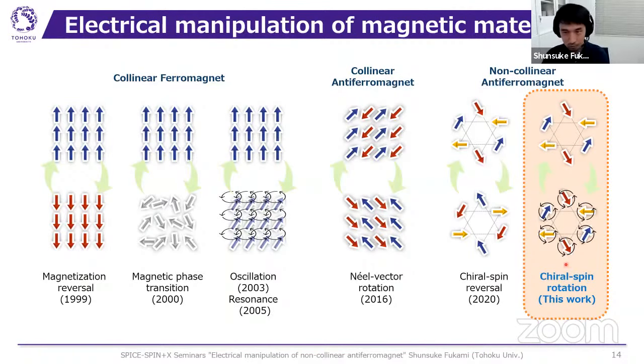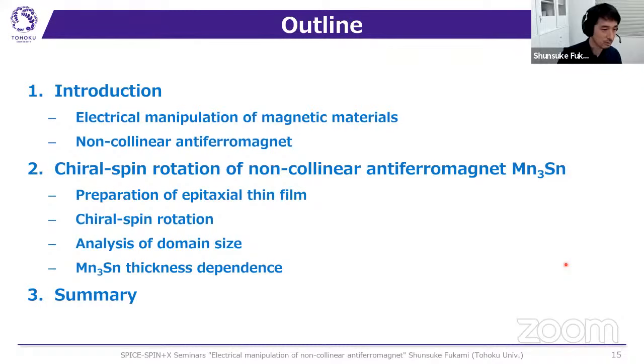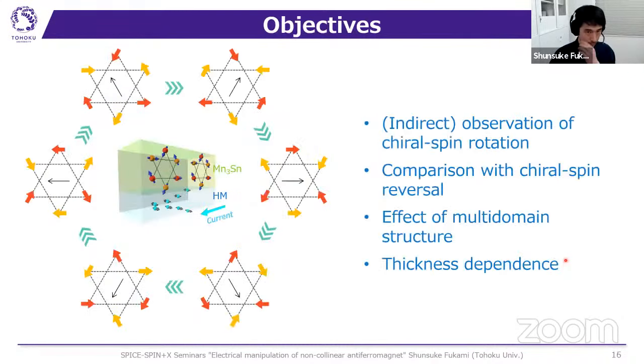Okay, so now let me move on to the main part. The objective of this work is to observe the chiral spin rotations. This is the schematic of the chiral spin rotations. As you can see, each sublattice rotates as shown here, and the residual magnetic moment also rotates as shown here. To observe this behavior, we need to prepare epitaxial structures in which the Kagome lattice can be controlled with respect to the injected electron spins. So we first try to prepare the epitaxial heterostructures.